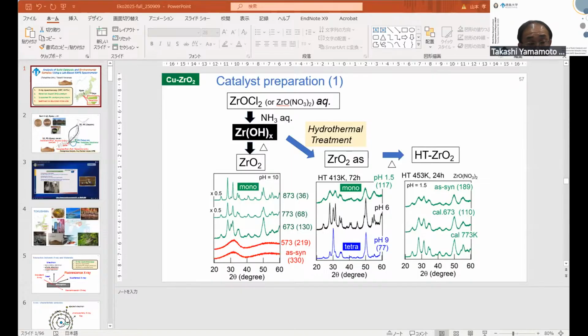I'll talk about the catalyst preparation procedures and how to control the crystalline phase. The preparation procedure is quite similar. Firstly, the zirconium salt is hydrolyzed to obtain zirconium hydroxide, and calcined without metal additions. Below 300 Celsius it is amorphous, but above 400 Celsius the monoclinic phase appears. Using this amorphous phase for hydrothermal treatment, different pH gives different phases: acidic conditions gave the monoclinic phase, and basic conditions gave the tetragonal phase.